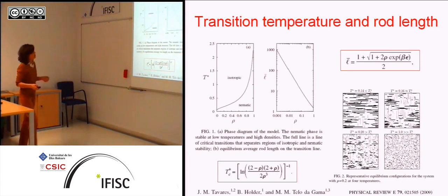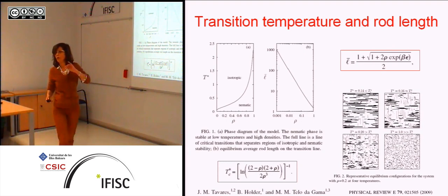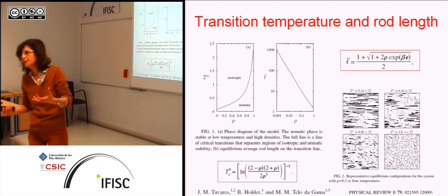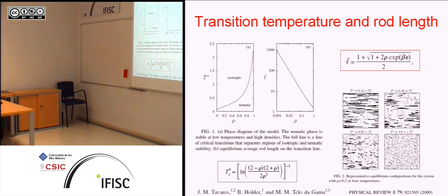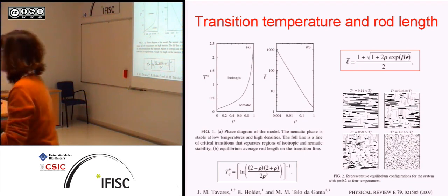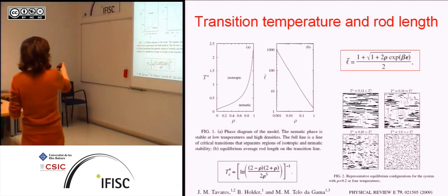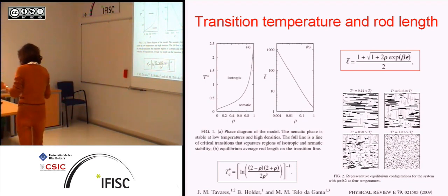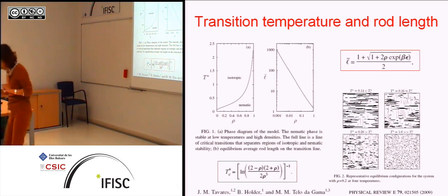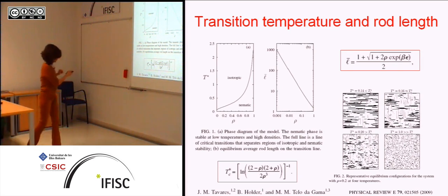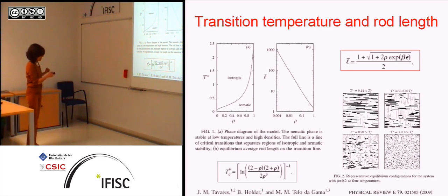Oops. So you can do the mean field theory for these. I'm not going to bother you with the analysis. It's quite simple to derive the free energy, the length distributions, the transition, and you find a continuous transition in mean field. It's always continuous, at least for this discrete orientation model in 2D. And remember that now, because you have an energy, you have a temperature where the system orders. Nematic is an ordered phase, like this.